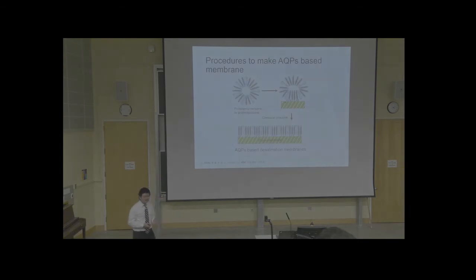This is how we designed the project, and this is how the membrane was made in the literature, if you can find it. Because it's a membrane protein, it will precipitate without specific shielding. So we had to protect this membrane protein inside a hydrophobic environment, like a lipid bilayer or a polymer bilayer. And then we fused these vesicles onto the support, and then we cross-linked them. So we formed this composite, an aquaporin-based desalination membrane.